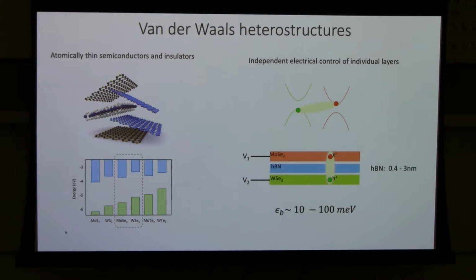But what we can do is stack them with a thin BN in between. With this exfoliation technology, we can control the BN thickness down to a single atomic layer, which is 0.4 nanometer, or we can choose any integer number of layers. So we'll focus on a range where the thickness is from, say, 0.4 nanometer to around 3 nanometers. Furthermore, we can put electrical contacts on individual layers. With these electrical contacts, we can apply bias or gate voltage so that we can inject electrons and holes into these two layers. It was estimated that the exciton binding energy with this kind of hBN thickness can be in the 10 to 100 milli-electron-volt range. 100 milli-electron-volts, if you convert it into temperature, is about 1000 Kelvin.